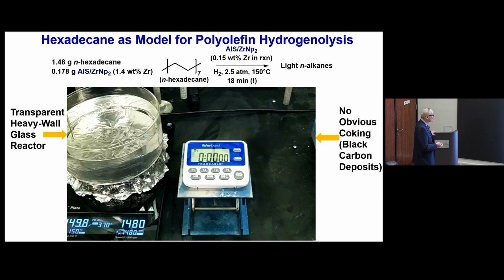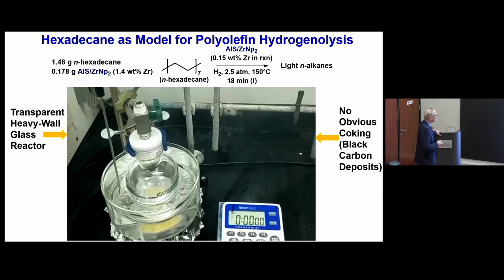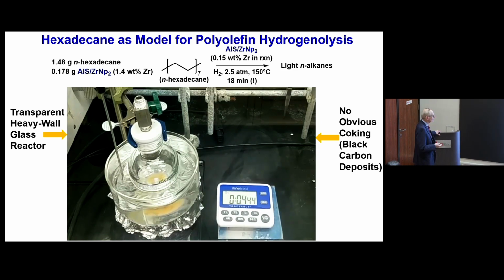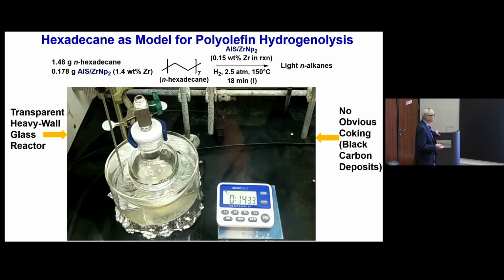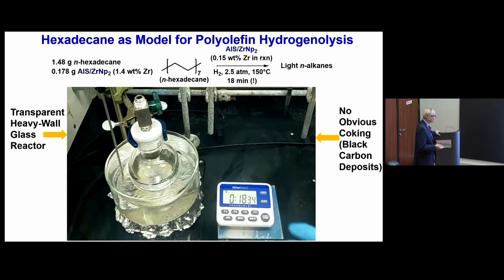In fact, this is the kind of thing you want to show to a program manager in Washington. I mean, it's only 150 C, and in 18 minutes, it's all gone. A lot of the platinum metal catalysts that the Santa Barbara group are using, you look at the reactor and it's just full of black stuff, and that's called coking. All kinds of carbonaceous deposits. This is very, very clean chemistry.